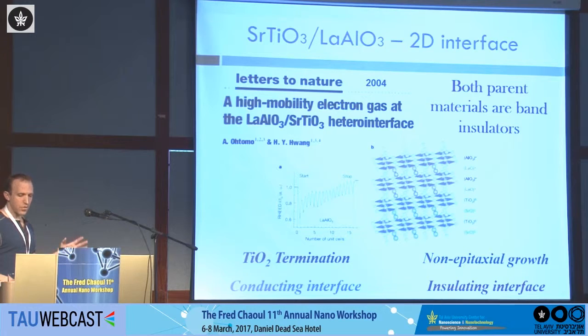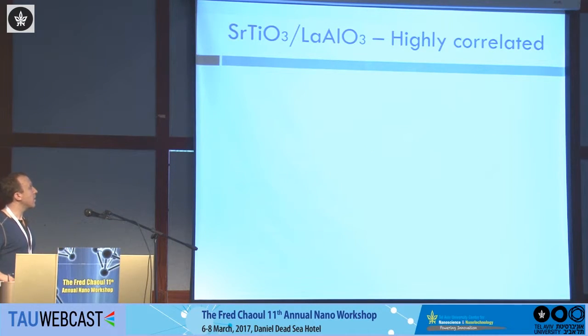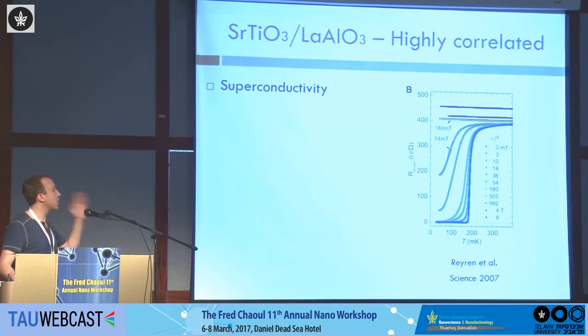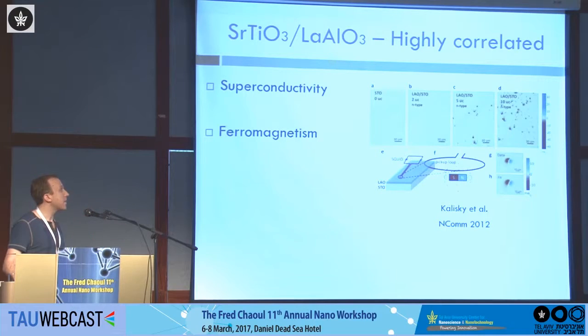Why is this material interesting besides its two-dimensional conductivity? It is highly correlated. What does it mean that it's highly correlated? It means that the electrons have interaction between themselves. How can we see it in experiments? First of all, this material is superconducting under 350 millikelvin. This is the first measurement that showed that. Second of all, it's ferromagnetic. This is a scanning SQUID measurement from Beena Kalisky